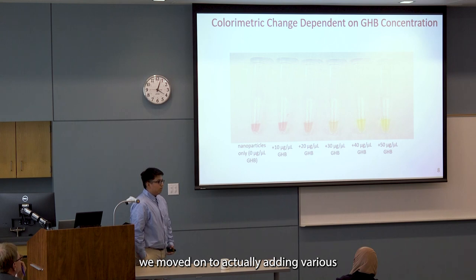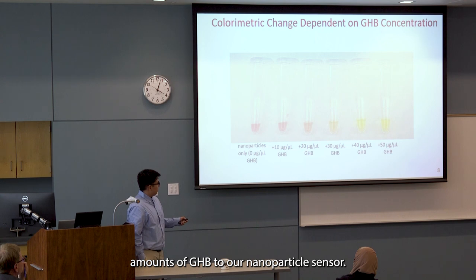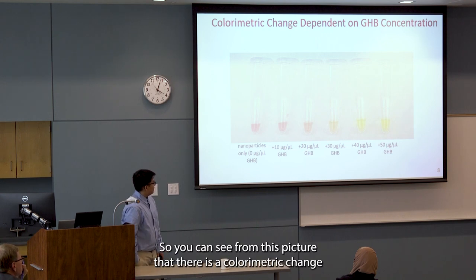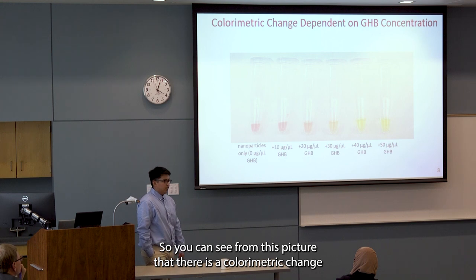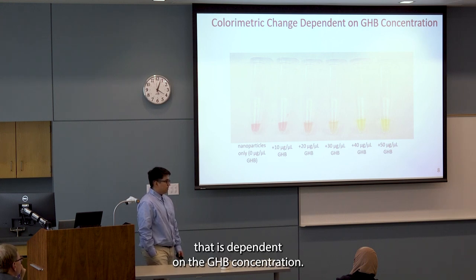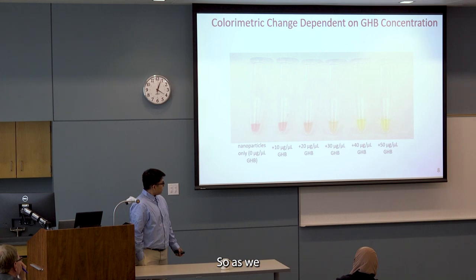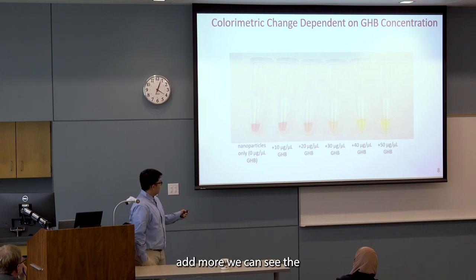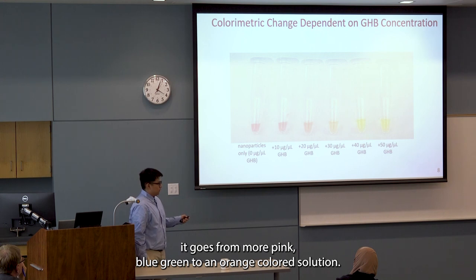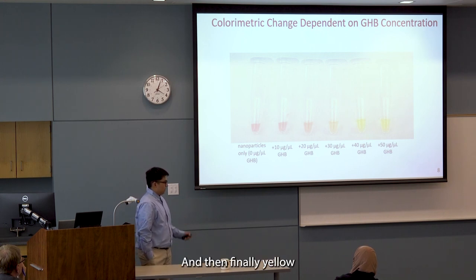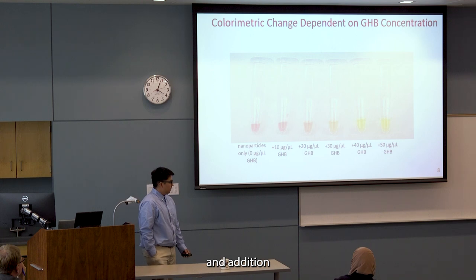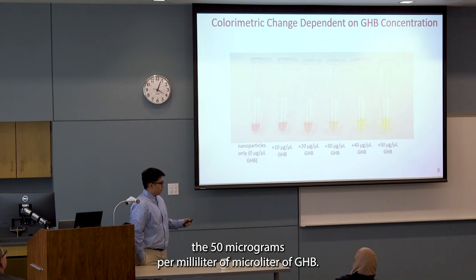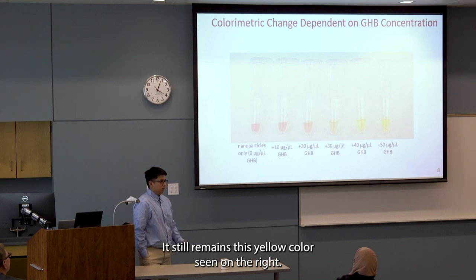Once we do this, we move on to actually adding various amounts of GHB to our nanoparticle sensor. And so you can see from this picture that there is a colorimetric change that is dependent on the GHB concentration. And so as we add more, we can see that it goes from more of a pink slowly into an orange colored solution, and then finally yellow. In addition, with addition of more GHB past 50 micrograms per milliliter of GHB, it still remains this yellow color seen on the right.